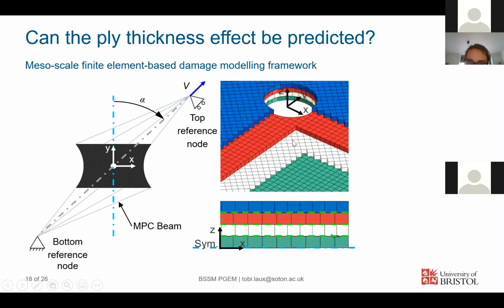And so the architecture of this model looks like this. So for the UD plies, they are a single element through the thickness. And also you can see that the mesh is fiber oriented. So in this ply, the fibers go like this. In the red ply, it's 90 degrees, 45, and 90 or 0 again. So if you use a continuum damage model, which we use here for the plies for fiber and matrix failure, then this mitigates some mesh-induced directional bias on the prediction of cracks in here.